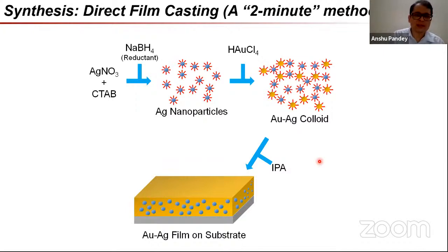So with that, let me change gears. As promised, I will just conclude quickly by describing the synthesis of this material. So as Vivek had pointed out in the very beginning of the talk, this is NaBH4. The entire thing is done using NaBH4 at all stages. So that is indeed the workhorse chemical for the entire synthetic process. What we do is we initially start off from, this is the direct film casting approach, and this is the fastest method to do it.